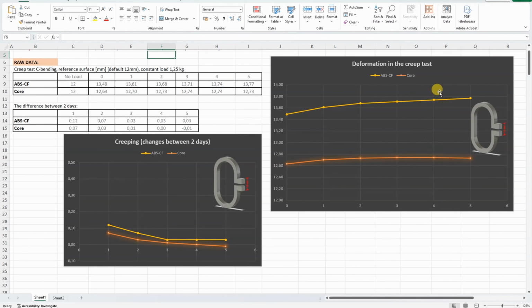On this graph we can see the distance between two reference surfaces, and we can see noticeably less deformation under the core version, but the creeping is the difference between 2 days, and that we can see on this other graph. And in both cases basically these are extremely small values, but yes, core is better in this case.